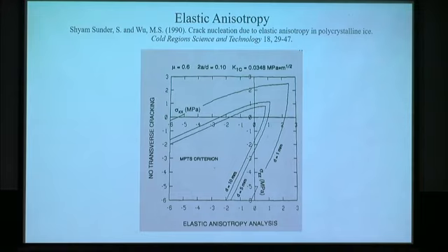We also did some analysis on crack nucleation for the multi-axial stress state. If you look at this axis, basically sigma xx is the vertical direction, and on the other axis, sigma zz is the horizontal direction. For uniaxial loading, you can see that the compressive stress is of the order of minus 2.5 megapascal if the grain size is maybe 5 millimeters.